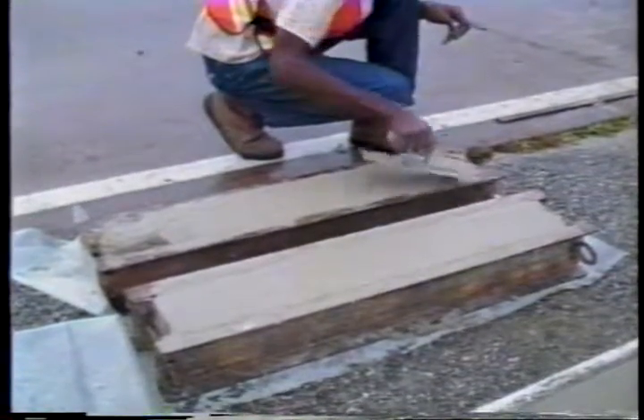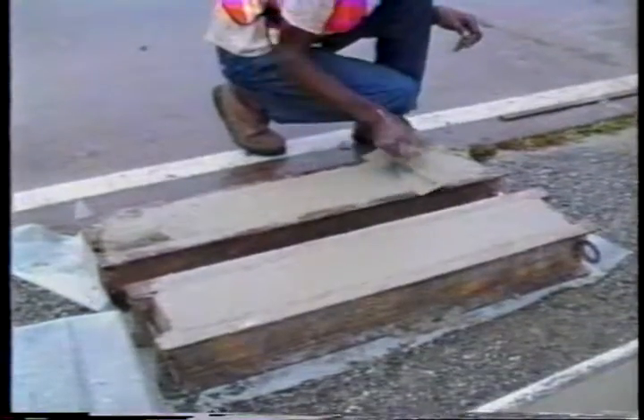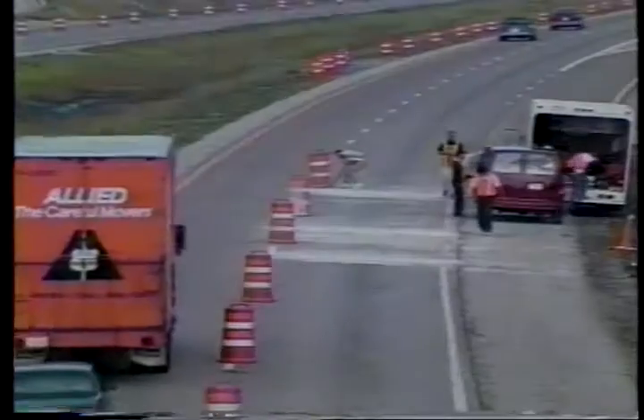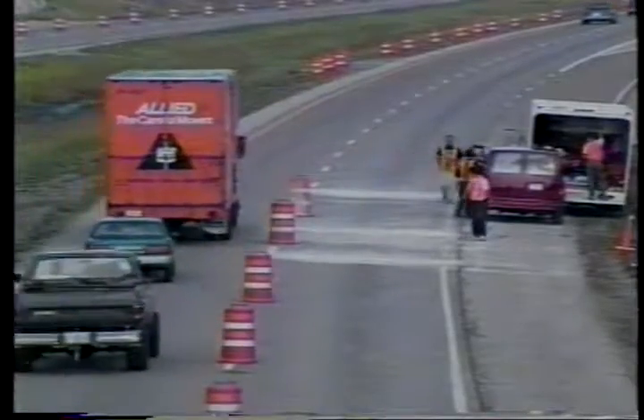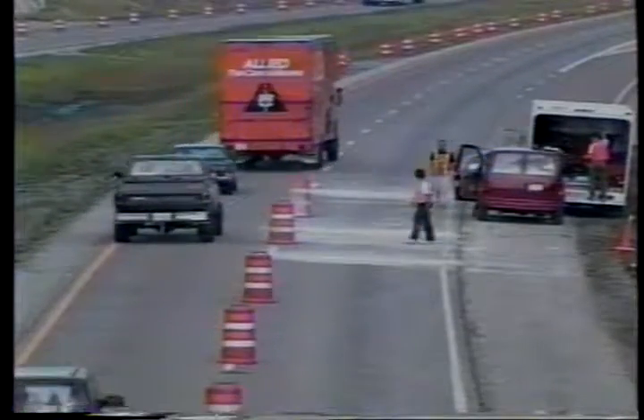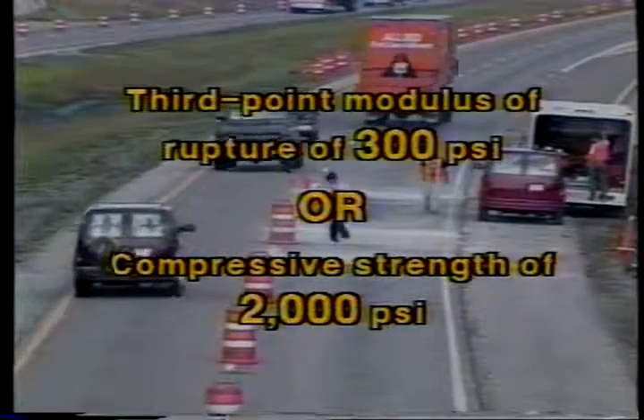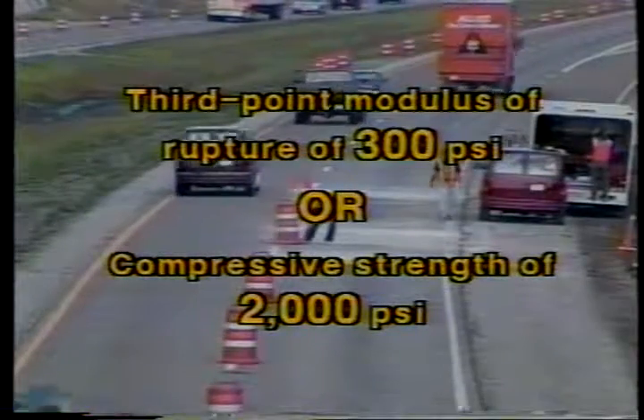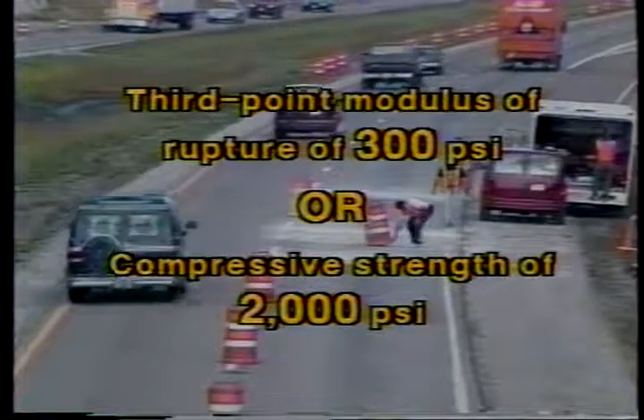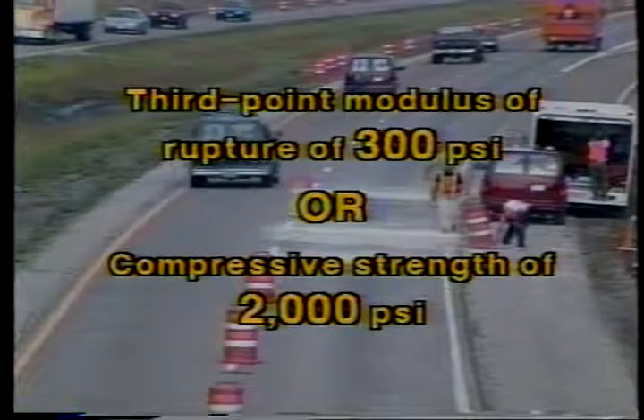Flexural testing of 6-inch beams also provided good results. Full-depth repairs of up to 12 feet long can be opened to traffic without adverse effects when the repair strength reaches a third-point modulus of rupture of 300 psi or a compressive strength of 2,000 psi.